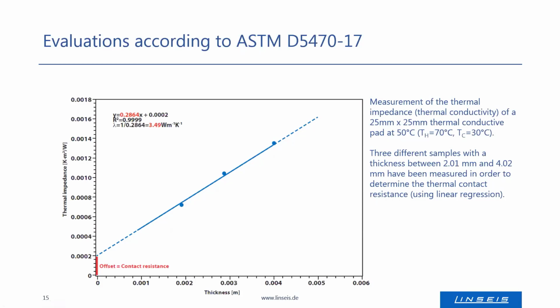If this measurement is performed under elevated temperatures, the thermal conductivity changes typically, and thus the slope of this linear curve will change as well. Furthermore, if the pressure on the sample is increased, the offset typically gets smaller because of better contact from the sample to the meter bars. Then this offset will be lower.